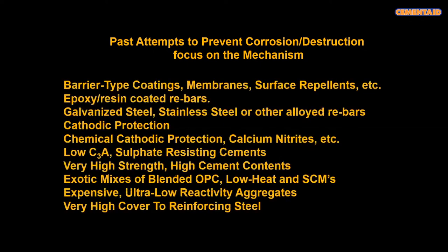If you're worried about alkali aggregate reaction, perhaps importing very low reactivity aggregates in some cases. Or finally, accept the inevitable, the chlorides are going to get in, and have a very high cover to the reinforcing steel. The downside to that, obviously, the greater the cover, the more the concrete is likely to crack.